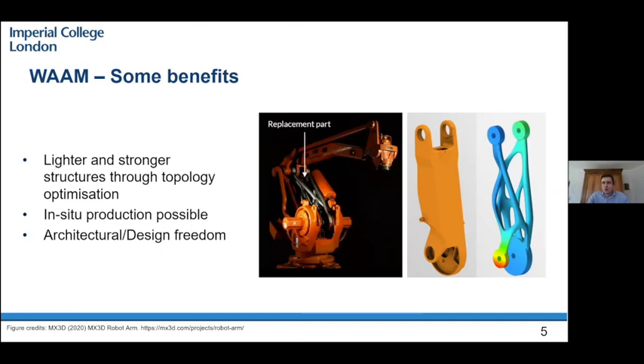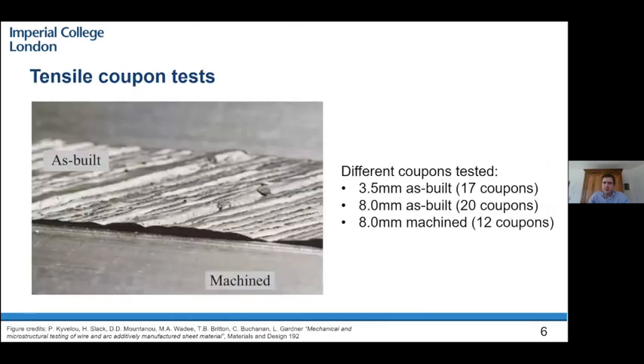So how do we want to help assessing these structures? Well, we started with tensile coupon tests. Tensile coupon tests of different materials in WAAM. This means we had different surface finishes, one as built, one surface finish machined, which means that the surface undulations that are present due to the additive manufacturing step have been removed with an end mill. Different thicknesses were also tested, namely 3.5 and 8 millimeters.